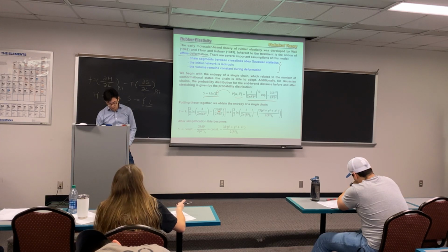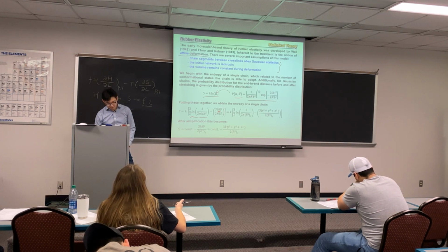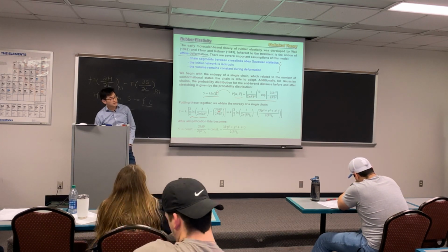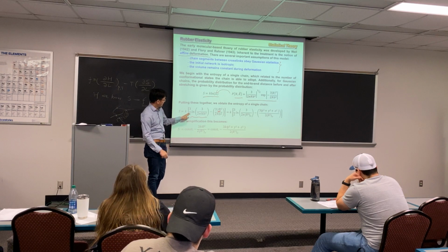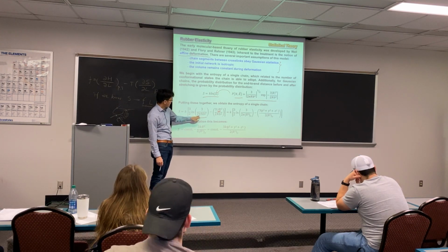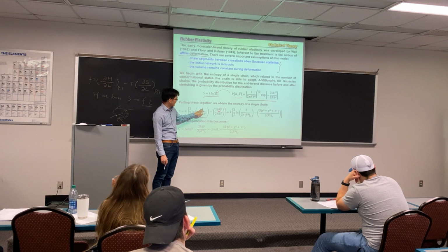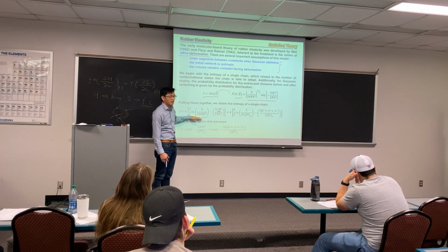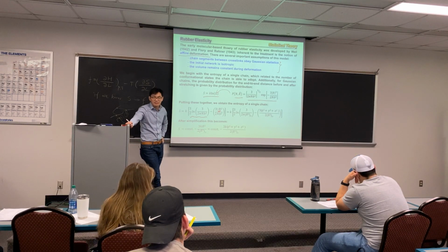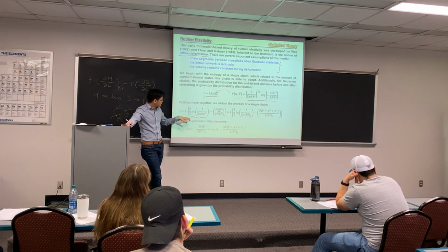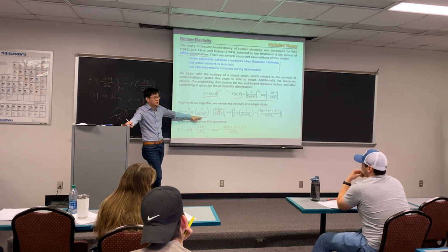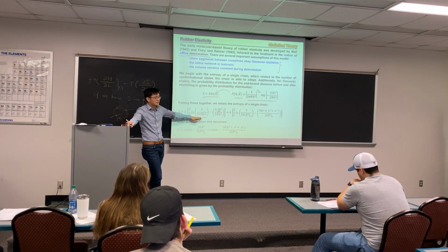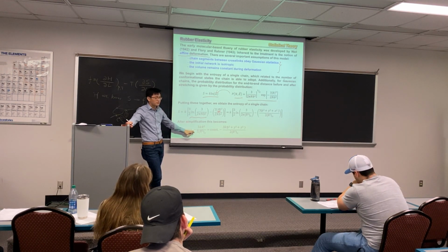This will be the 2/3, which agrees with the first part. As we can see, if you pay attention to the value there, it's 2/3, right? And you have ln of 2 pi m b squared over 3. Does it depend on R? It does not, right? So that means this part of the entropy is a constant. It doesn't change with the degree of strain you pull your polymer chain. As you can see, this says constant for this part.